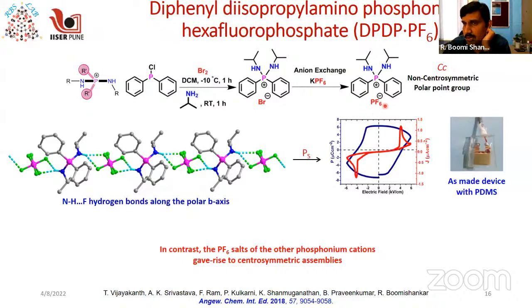So we wanted a polyatomic anion, and the PF6 salt of this diisopropyl diphenyl phosphonium compound was found to be ferroelectric along the polar b axis, because the molecule has a non-centrosymmetric space group, Cc, and the small c is along the b axis, which is a polar axis. It shows a typical ferroelectric P-E loop like this, and a J-E curve with the peak at the coercive field. We also subsequently made a composite material of this in PDMS polymer, made a lab scale device, and used it for energy harvesting applications. I will talk about the applications of this material in the subsequent slides.